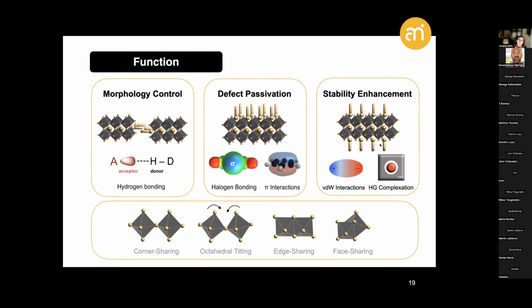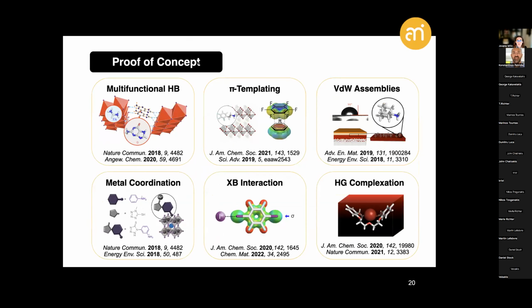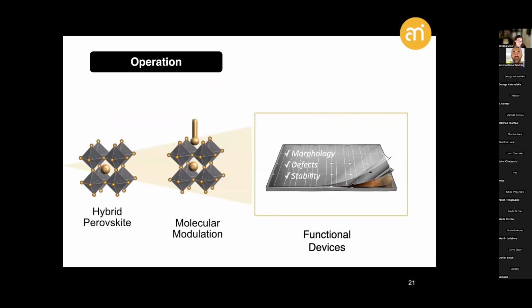Now, to really demonstrate the proof of concept for relying on some of these approaches to address the present challenges and tailor the properties in these materials, over the past few years, we have looked into a number of tailored molecular components, some of which are illustrated here, that rely on different supramolecular interactions, from hydrogen bonding and metal coordination through pi templating effects, halogen bonding, different hydrophobic van der Waals assemblies, or since recently host-guest complexation, each of which really demonstrating different capacities to tailor the properties and enhance the stabilities of these materials that are primarily related to these three general functional categories, such as the morphology control, defect suppression, or a variety of mechanisms for stabilizing these systems, both extrinsically and intrinsically.